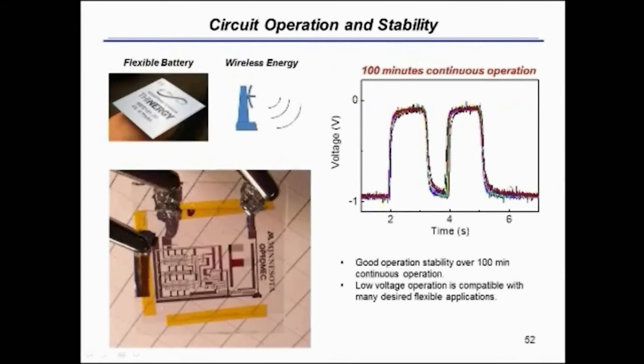And here on this slide, I show you in the upper right, the output pulses to one electrode, here's the pixel here on the left, the output pulses to one electrode for 100 minutes of continuous operation in a dry nitrogen environment. So there's no encapsulation on this device, we just operated it in the glove box. But you can see very little degradation in the output curves.